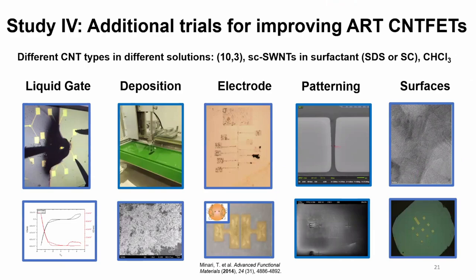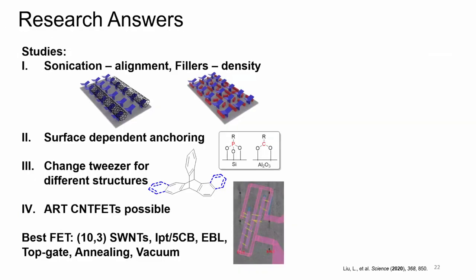So I know those are all positive results in the past couple of slides. However, research is not always positive. So I did many different attempts, like an ionic gel gate, Langmuir-Blodgett deposition, and gold nanoparticles in an organic coating. All that was interesting to delve into, but it didn't really work. And that's not going to be a paper, but it's interesting science. And so overall, I did obtain research answers for all the studies I did. Sonication was one of the modifications we did to increase alignment, but it decreased density.